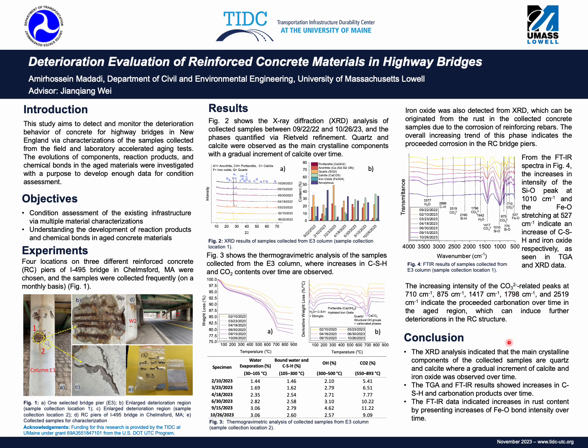In conclusion, our study provides valuable insights into the deterioration of concrete materials in highway bridges. The main crystalline components, quartz and calcite, in the XRD analysis show a gradual increase over time, which is the indication of ongoing degradation in the reinforced concrete materials. The XRD, TGA, and FTIR analyses all show increases in CSH content, carbonation products, and rust content, suggesting corrosion in the reinforced concrete bridge piers.